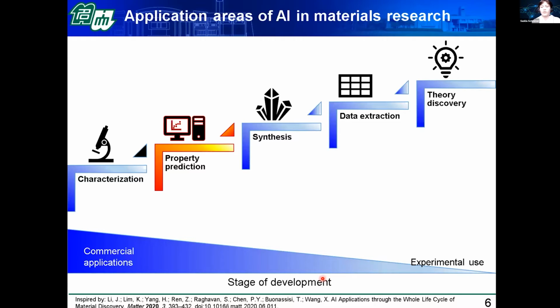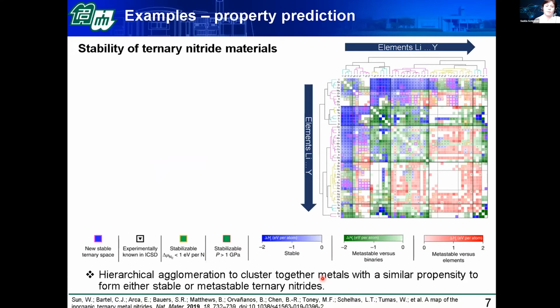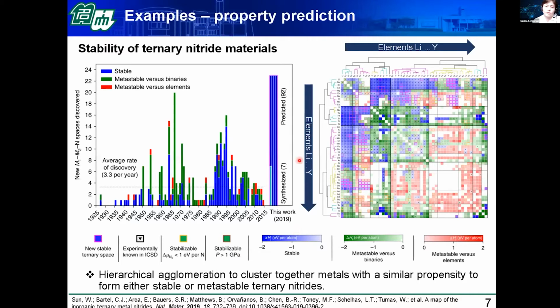In the field of property prediction or materials discovery, which is also relatively developed, I would like to show an example from nitride materials, specifically ternary nitride materials, in which hierarchical agglomeration was used to cluster together metals with a similar propensity to form either stable or metastable ternary nitrides. And this was used to predict the thermodynamic stability or metastability of ternary compounds that are shown in this map. So the position shows the composition, and the color coding refers to the stability that was predicted. Using this method, it was possible to predict a large number of new ternary nitrides. And the authors also were able to validate their results by synthesizing a subspace of those materials already.